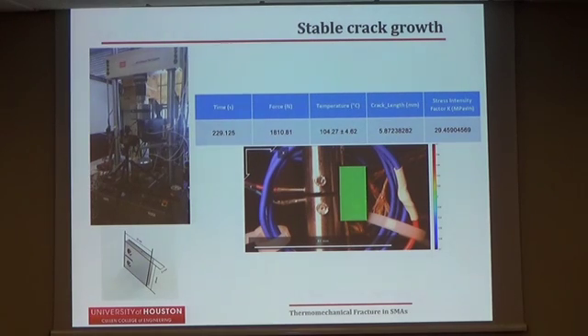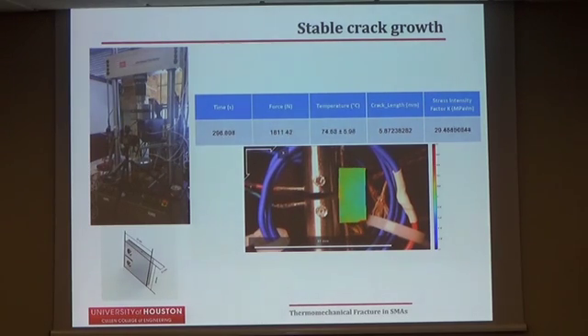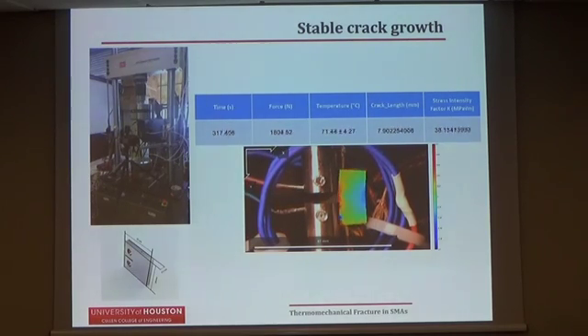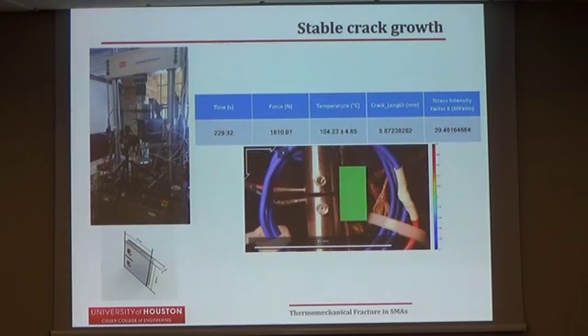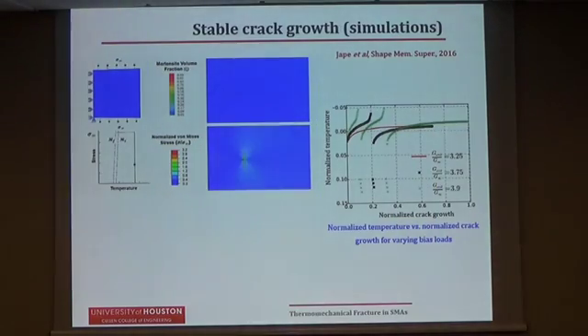We wanted to check whether there is a possibility of stable crack growth in more stable crack configurations like CT specimens, compact tension specimens. And we ran those experiments and we indeed find stable crack growth. Now, why is that? Imagine that in all those specimens we apply a mechanical load and then we start cooling, right? Now, once the crack starts growing, the transforming material that is left behind the crack tends to close the crack. So although the unbroken ligament becomes smaller and smaller and it needs to withstand the constant load, still we don't have an unstable crack. There is a stable crack growth regime, and we have simulated this behavior.